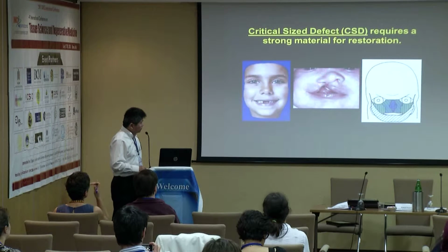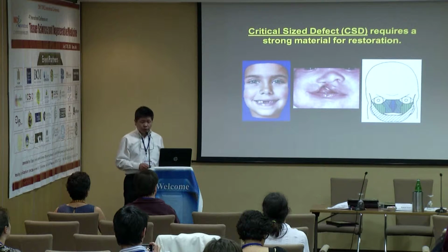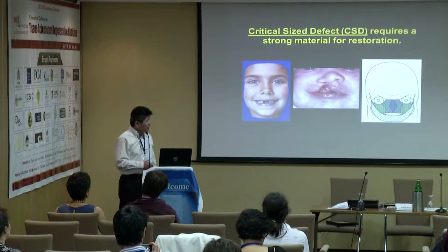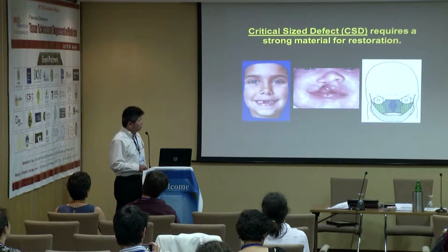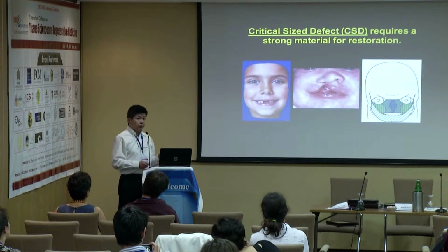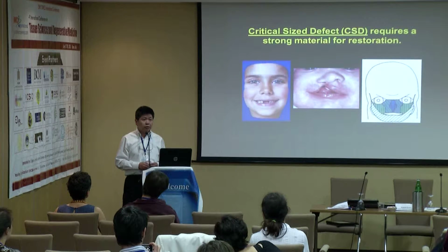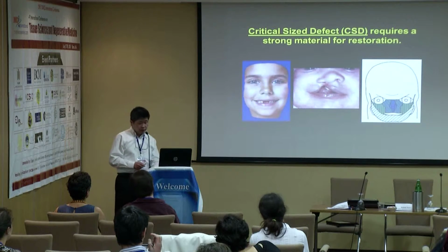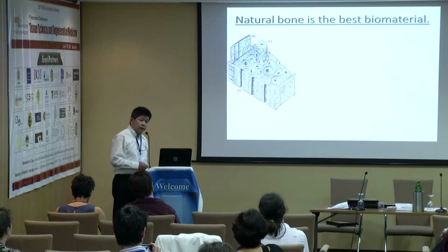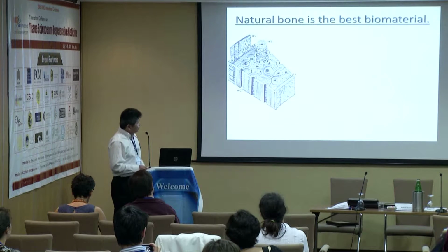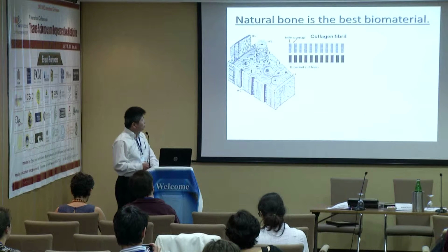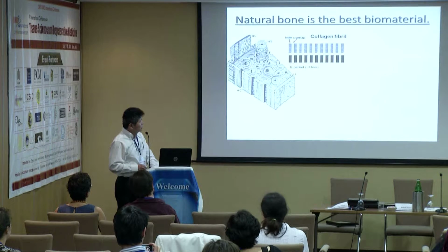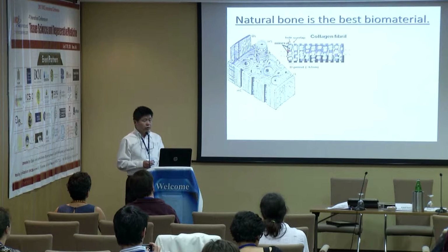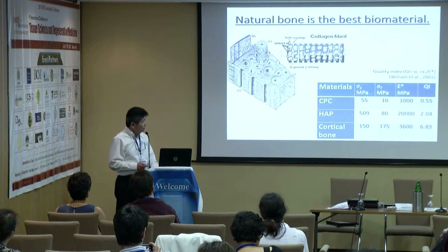When people have a defect, we need a material to repair it, and we need cells to repair it. The key is that in some areas, and some other areas not shown here, when the defect is substantial, you need a material which can support the loading. Currently we don't have that kind of load-supporting material, except natural bone, which is one of the best options. In natural bone, we have a nice collagen microstructure and a very good inorganic crystalline binding to the organic material, with very detailed chemical binding. Because of that, they can provide very strong strength.